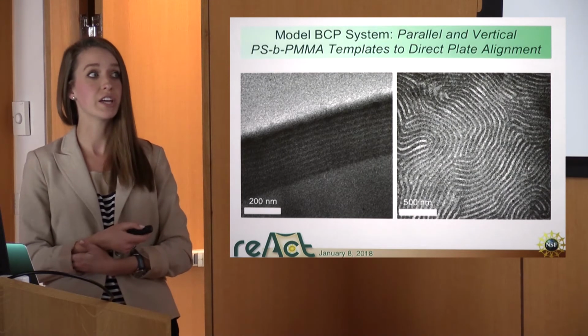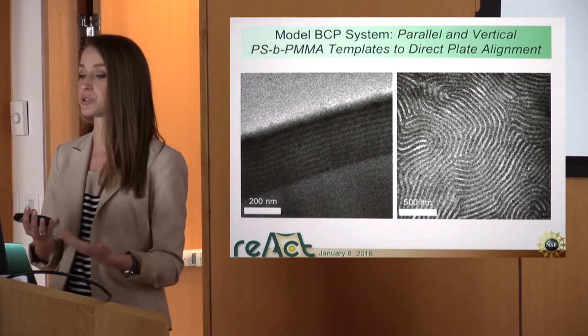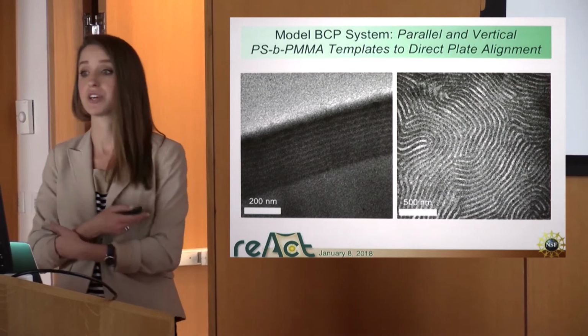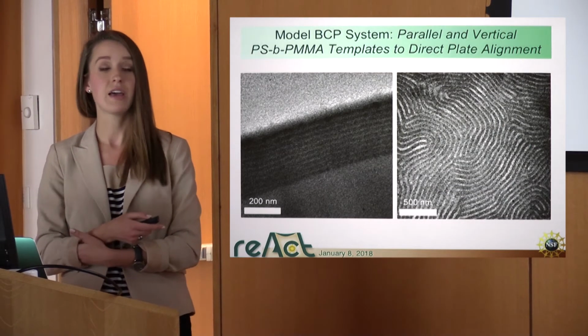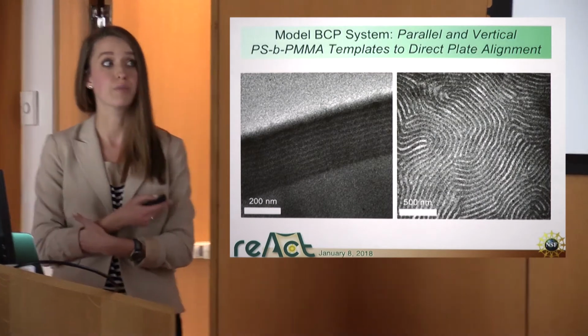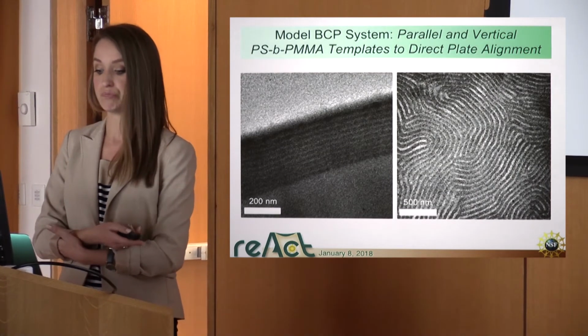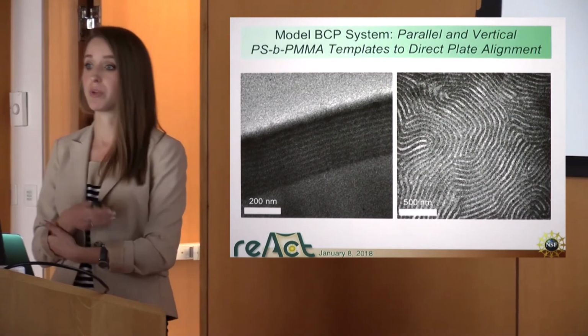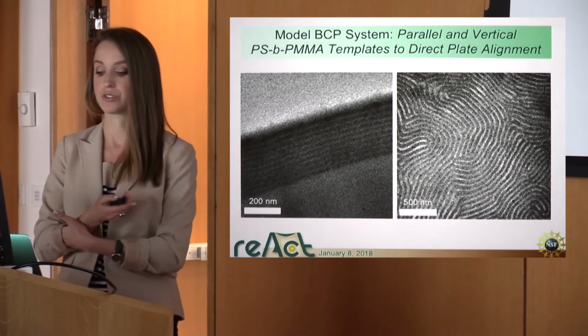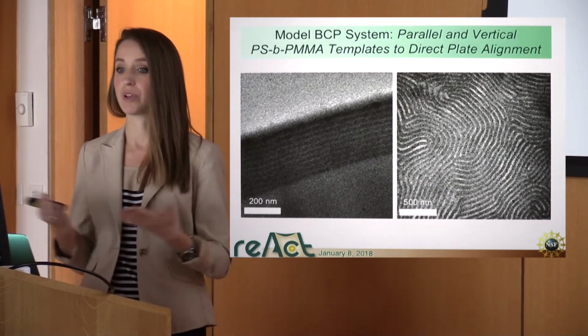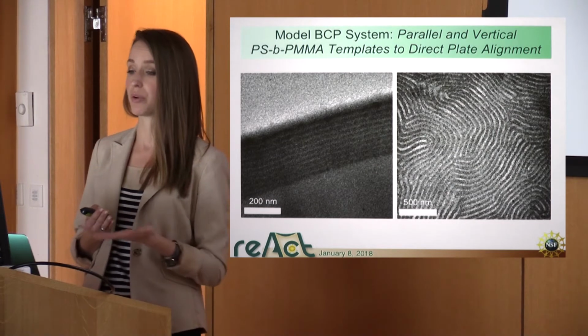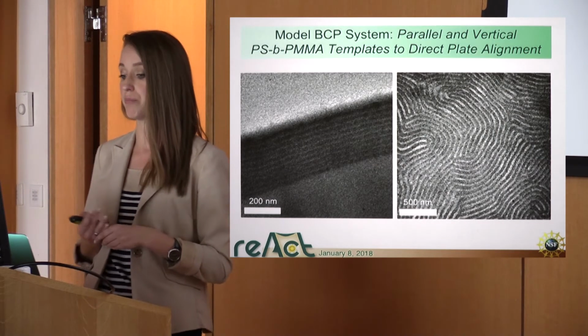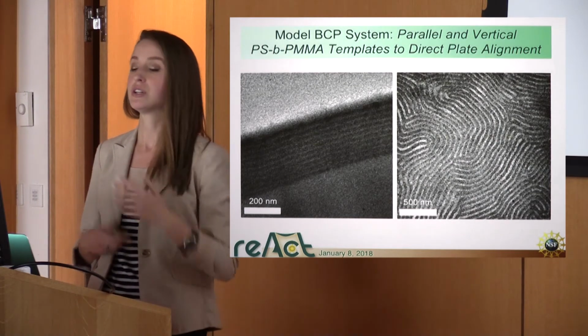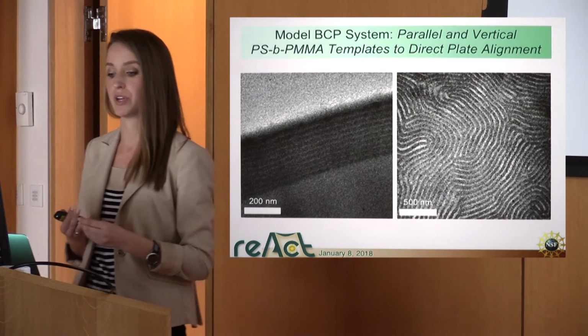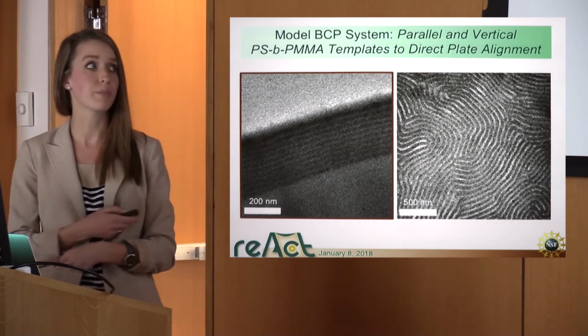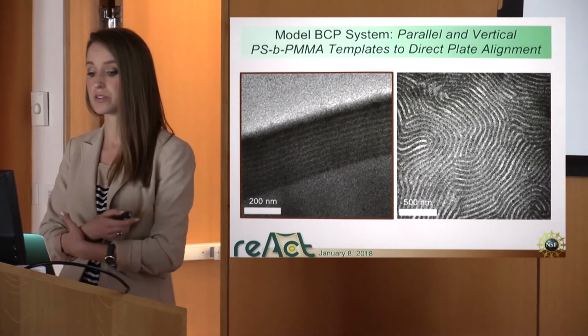And then if I change the surface chemistry of the substrate, making it neutral to both the blocks, I can actually get vertical lamellae. Here we're looking at a top-down image of the same block copolymer in a thin film with the domains oriented perpendicular to the surface. So now I've created a template with domains oriented parallel to the substrate and domains oriented perpendicular to the substrate to serve as a guide for alignment of nanoparticles. For the purpose of this talk, I'm going to focus on my work with the parallel system.